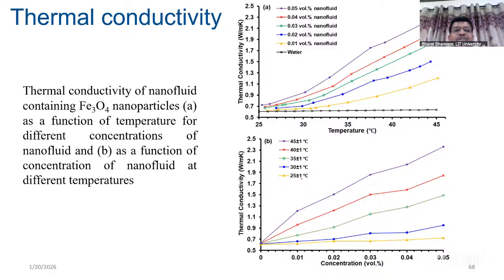Then we measured thermal conductivity as a function of nanoparticle concentration, calculated at different concentrations and different temperatures. We observe that with the addition of nanoparticles, thermal conductivity gets improved, and also with increasing temperature, both factors contribute. You can observe this in the data.